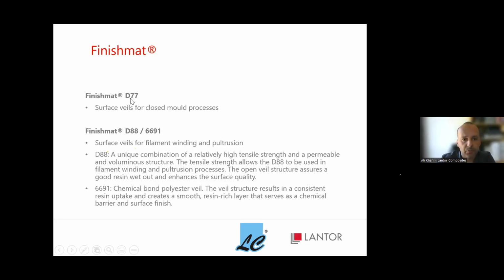So these are needle punched. This D88 is needle punched, and this 6691 is a chemical bonded polyester veil. And it also helps to uptake resin, basically having a very thin resin-rich layer on the top of the laminate, which serves as surface finish, also as a chemical barrier to protect the laminate.